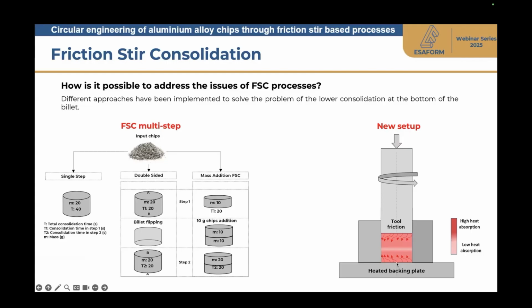The other possibility, of course, probably more complex, but more interesting, at least from my side, is to have a more complex fixture in order to carry out the process, and in particular to have a heated backing plate in order to increase the heat flux or to make it more homogeneous all along the section of the billet to be obtained.